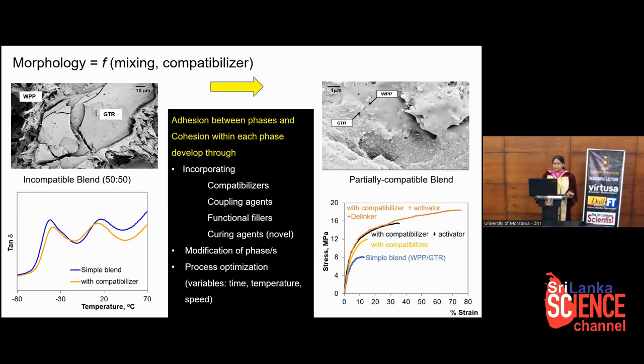The morphology is the key factor to obtain enhanced properties. In an incompatible blend, the SEM images show a gap between the two phases. During stretching, the two phases are separated and voids are created, and we can easily see a phase separation. But in a partially compatible blend, the two phases are overlapped and there is no separation. To enhance the properties of a blend, we have to incorporate different types of additives that will enhance the adhesion between phases, or enhance the cohesion within each phase.